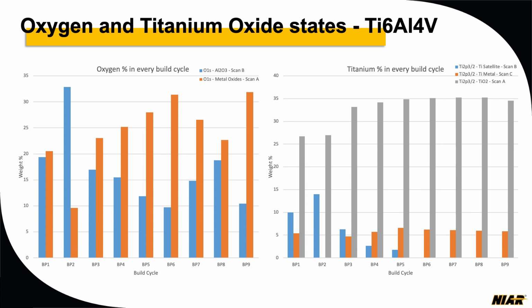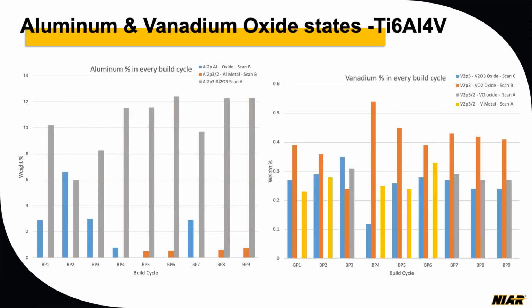For titanium, again, we are seeing a consistent increase, but at some point it leveled out, at around 30% weight percent. Then you have aluminum oxide. We got some variable results from metal to metal, slightly varied overall, but its tendency is constantly increasing after every build cycle. Again for vanadium overall, the percentage has been consistent because the whole alloy is already at a very low percentage, so we didn't see much of a difference from one point to another.